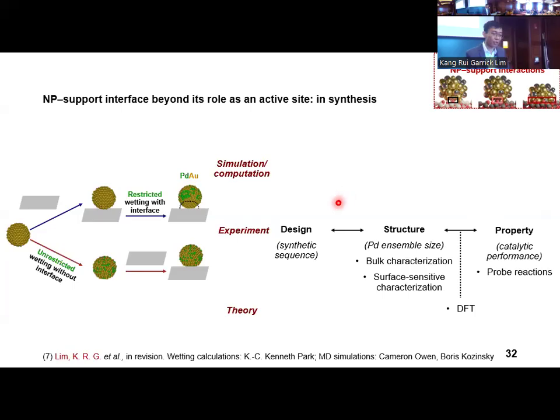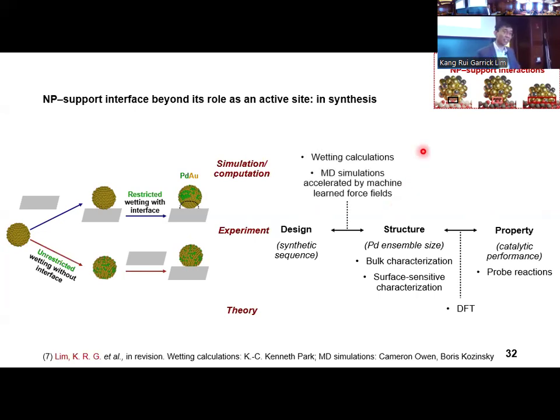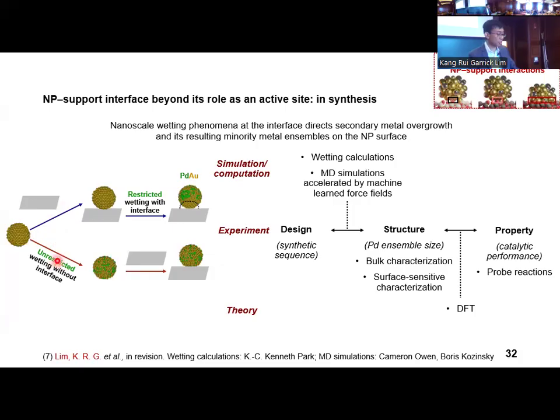Next, to understand how the initial catalyst design produces the types of palladium ensembles we observed, we performed numerical wetting calculations and molecular dynamic simulations accelerated by a machine-learned force field to understand palladium wetting on the gold nanoparticle surfaces and palladium migration during high-temperature calcination treatments to prepare the catalyst. We report that the synthetic sequence should not be chosen arbitrarily, as nanoscale wetting phenomena at the interface plays a non-innocent role in bimetallic palladium gold nanoparticle catalyst synthesis and their resulting catalytic performances.